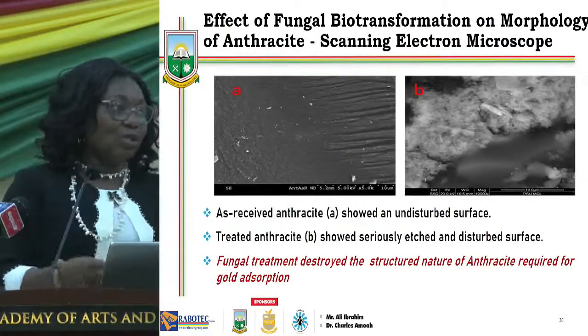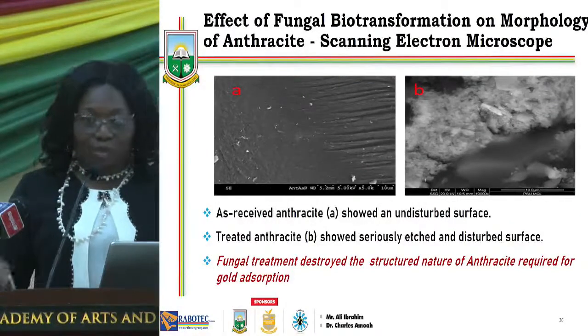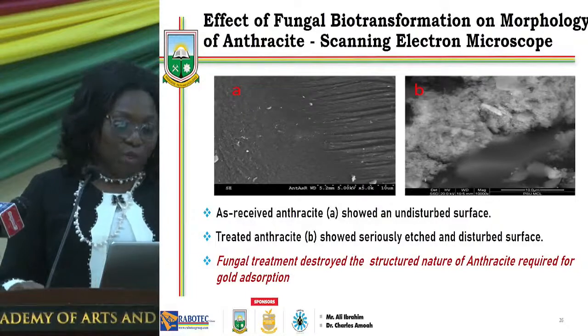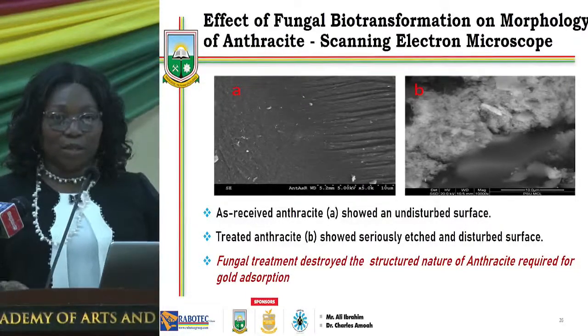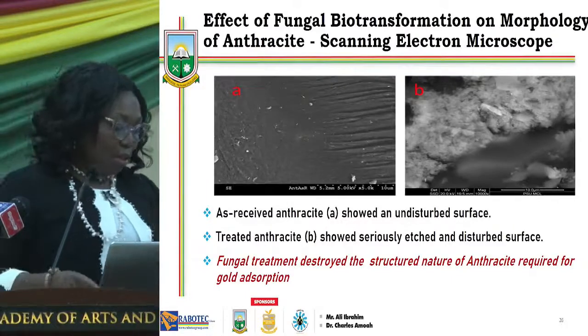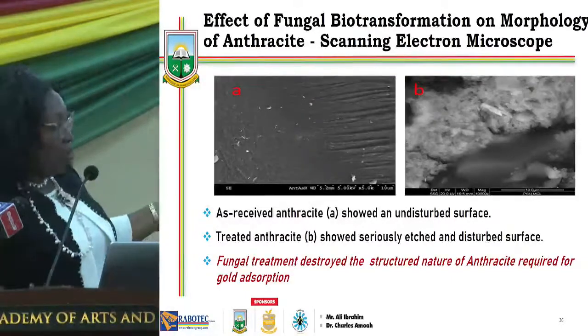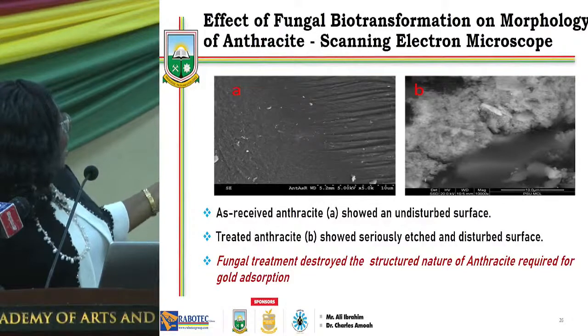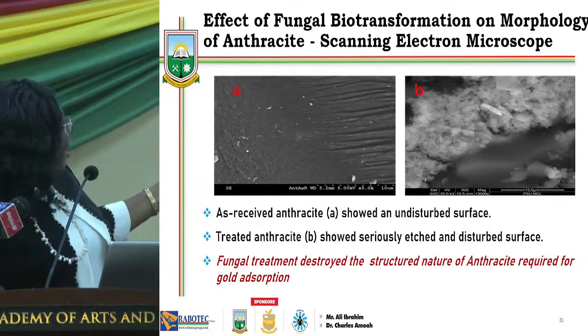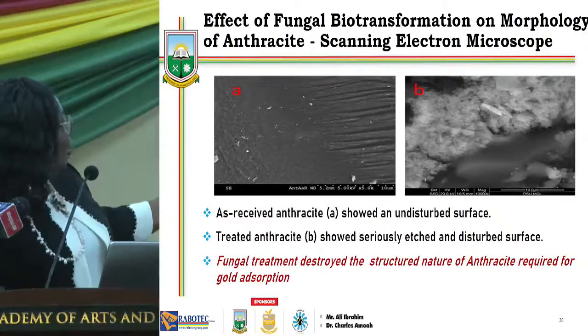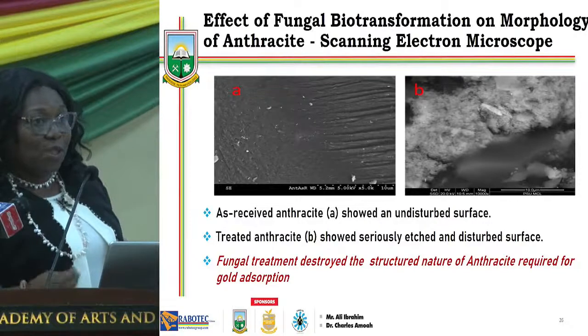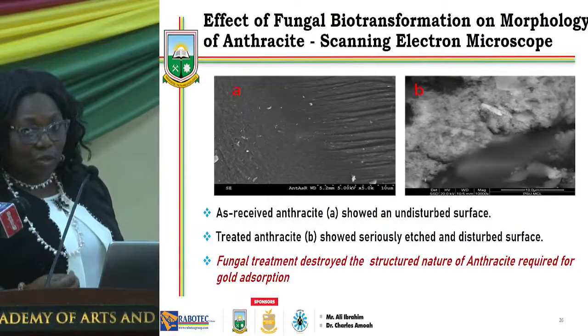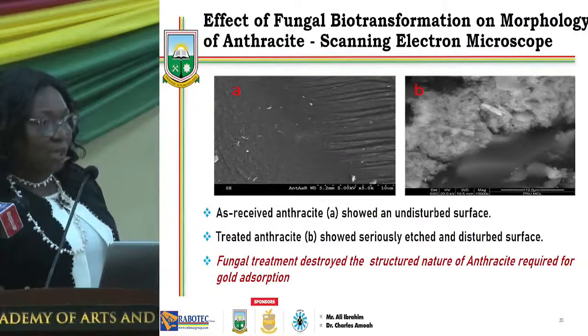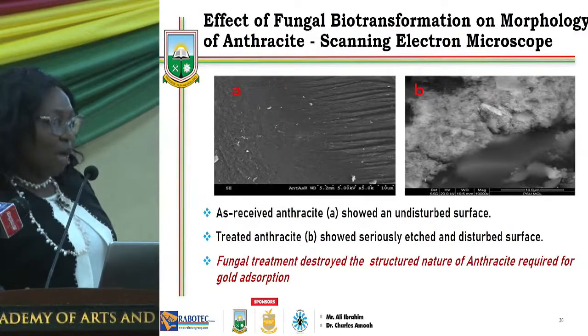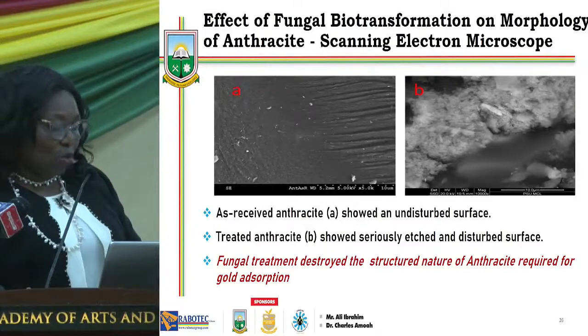What is it that the fungus is doing to the surface of the carbon for gold absorption to reduce? So we use some characterization techniques. The picture here is SEM. A is showing the as received anthracite, which has a well-structured surface, and after fungal treatment, we see an amorphous surface. Such an amorphous surface will not help with gold absorption, and therefore it's one of the reasons why the ability to absorb gold reduced.